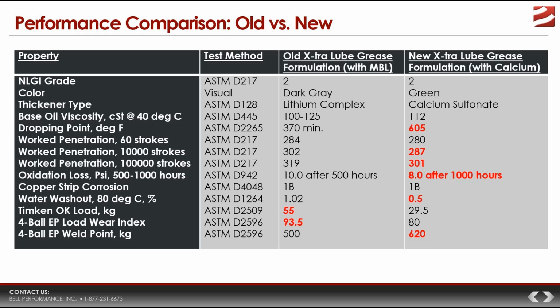If you compare the old X-tra Lube Grease and the new X-tra Lube Grease with respect to changes in work penetration, you see some significant differences. At 60 strokes, they're both pretty much the same, which you'd expect since they're both number 2 greases, 284 versus 280. At 10,000 strokes, the old X-tra Lube Grease has gone up about 18 points, from 284 to 302, which is okay. But the new grease only went from 280 to 287, a change of just 7 units. That's a significant difference.